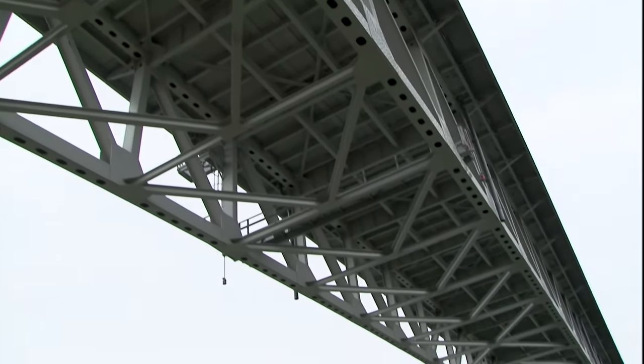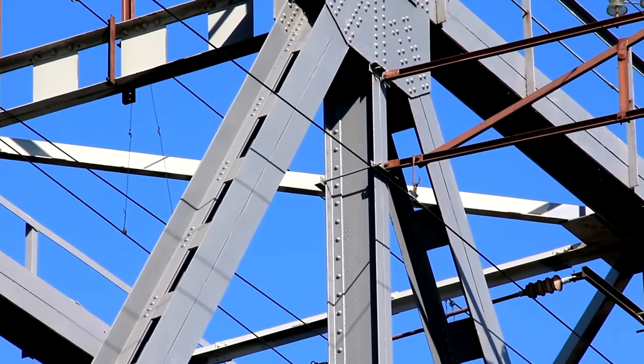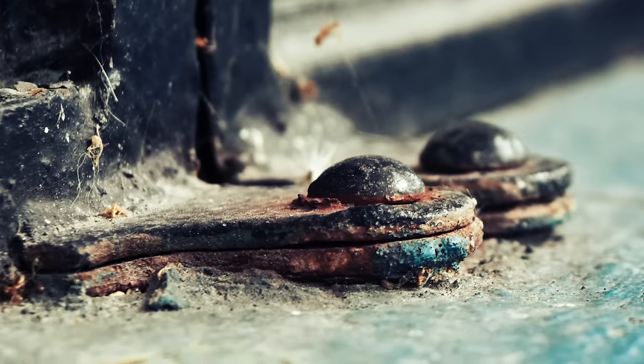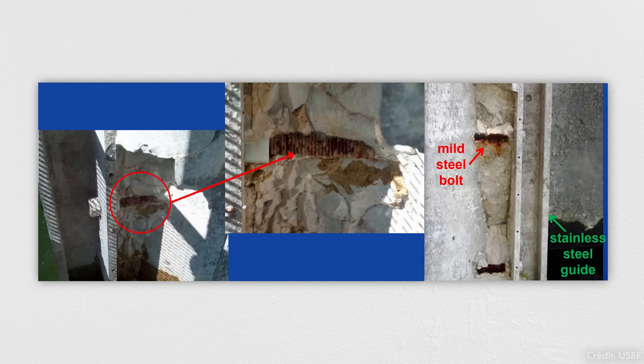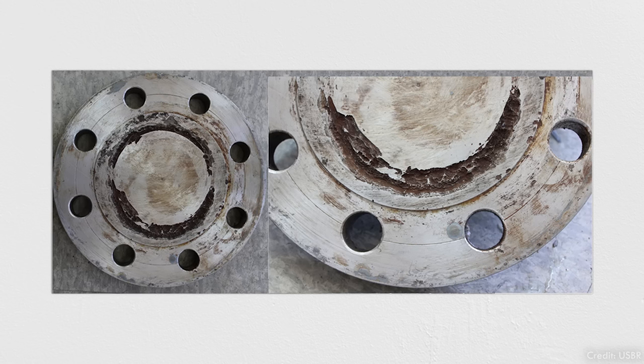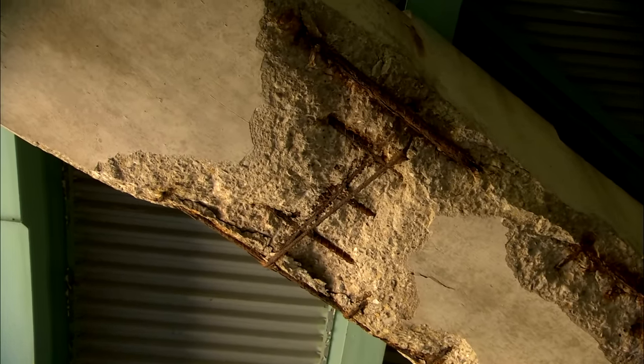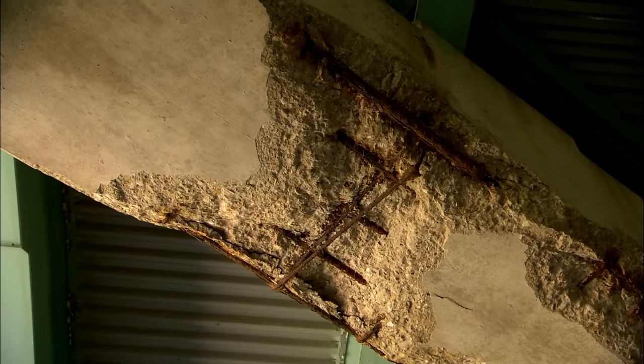You're probably familiar with uniform corrosion that happens on the surface of metal, like the beautiful green patina of copper oxides and other corrosion compounds covering the Statue of Liberty. But corrosion takes many forms, and corrosion engineers have to be familiar with all of them. These engineers know the common design pitfalls that exacerbate corrosion — like not including drainage holes, leaving small gaps in steel structures, and mixing different types of metals. Corrosion can occur from the atmosphere or simply by allowing dissimilar metals to contact one another, called galvanic corrosion. Even using an ordinary steel bolt on a stainless steel object can lead to degradation over time. Corrosion can happen in crevices, pits, or between individual grains of the metal's crystalline structure. Even concrete structures are vulnerable to corrosion of the steel reinforcement embedded within — when rebar rusts, it expands in volume, creating internal stresses that lead to spalling or worse.